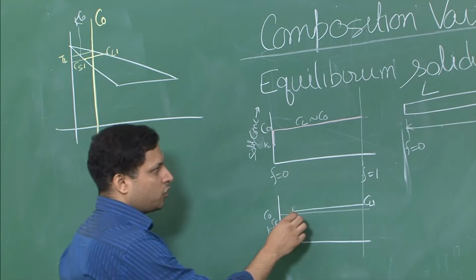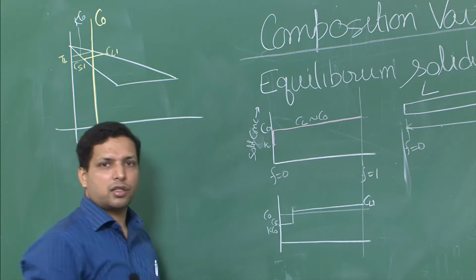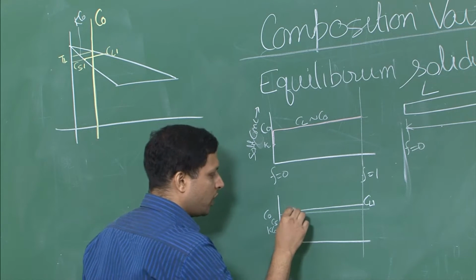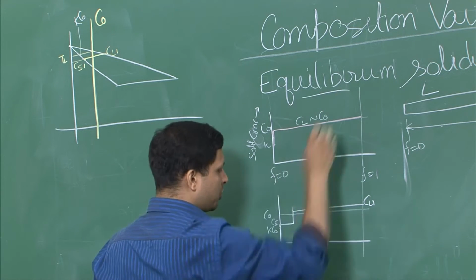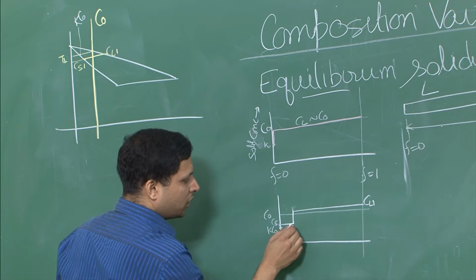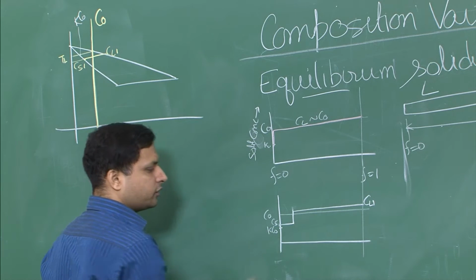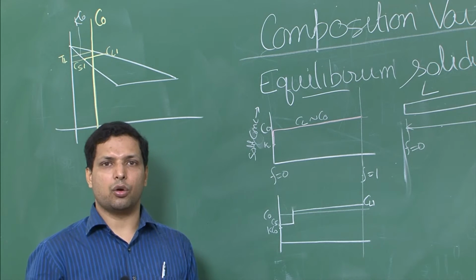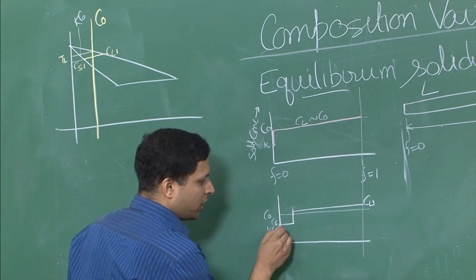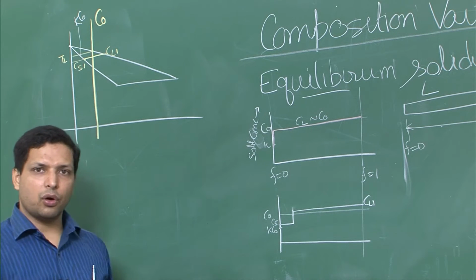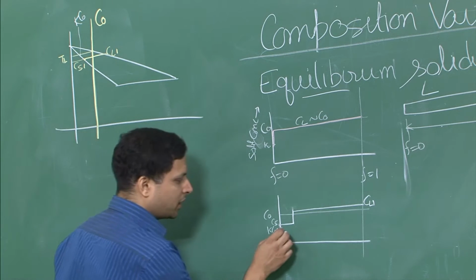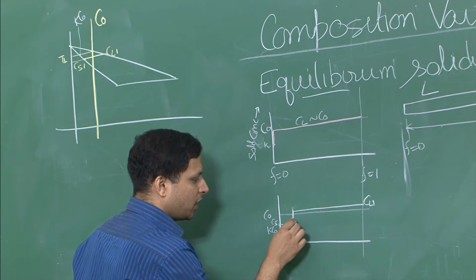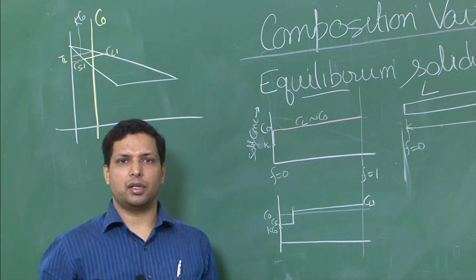Now it is very easy to understand that the overall liquid concentration increased because diffusion in liquid is very fast. But what we are also assuming when we say this equilibrium solidification is that the concentration of the solid part also gets homogenized very fast. The original solid that formed was at Kc naught, but by the time the solidification reached this stage, we are assuming that the overall concentration has also reached this stage.